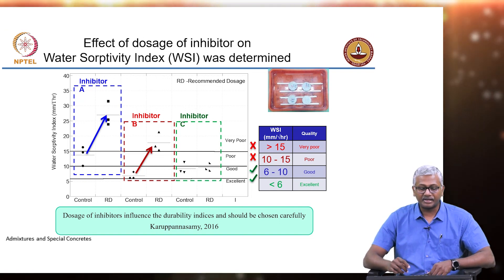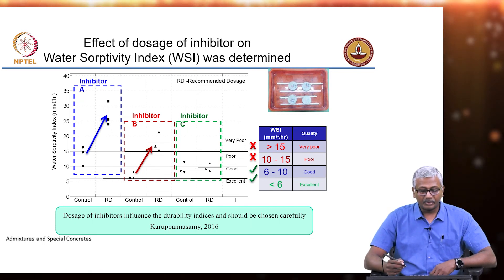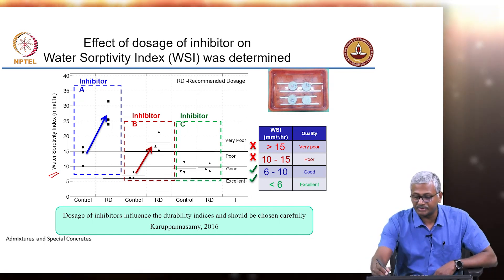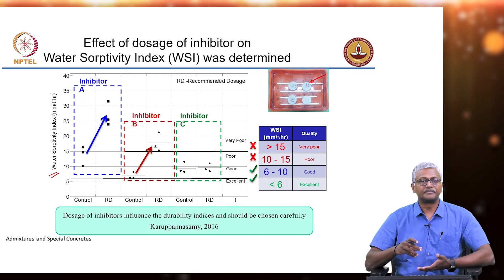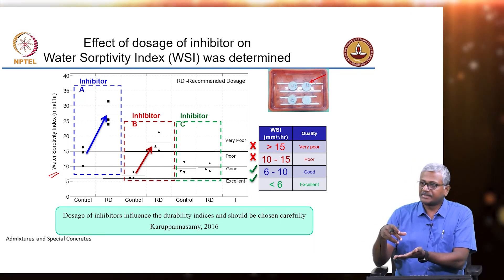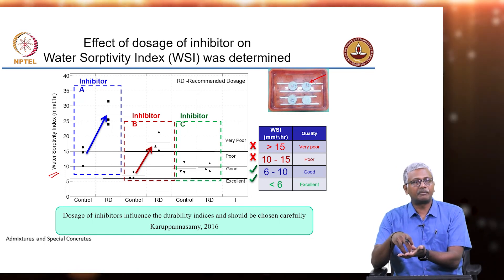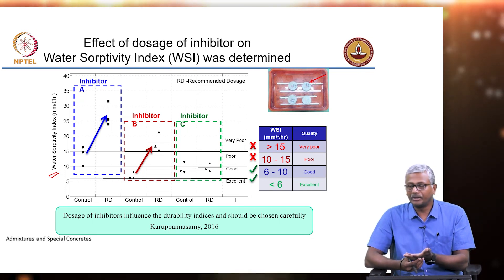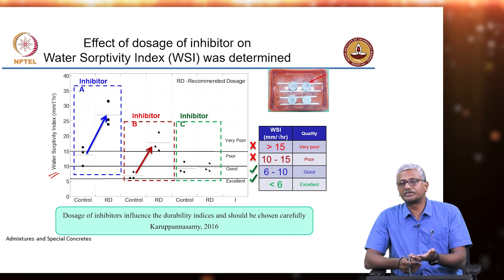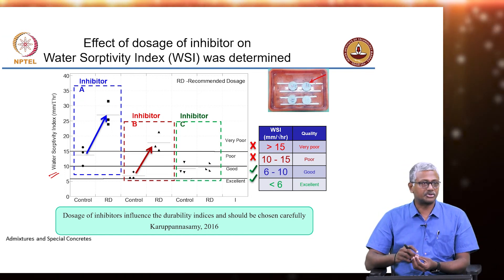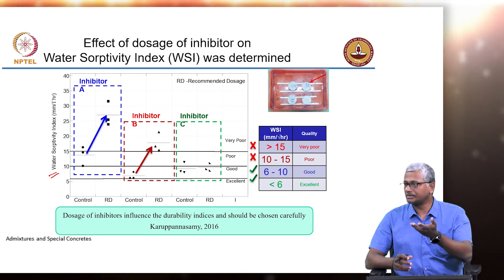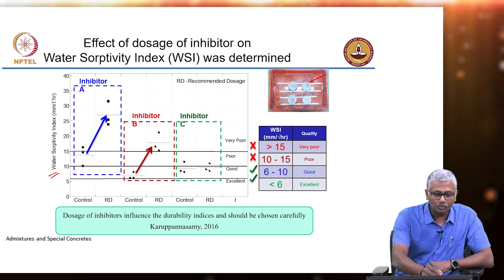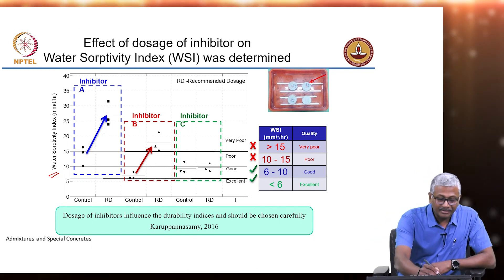Here there are three different types of inhibitors that have been looked at. You can clearly see that compared to the control values of water sorptivity — water sorptivity is a test where you take slices of concrete, expose the area, dry the slices so that they will be able to take in water by capillary absorption, then put them on a water tray. That water is basically imbibed by capillary absorption. So the more permeable or porous the material is, the faster it will imbibe moisture. And if the pores are connected, the capillary absorption will be significantly high. That is what is seen here — when you go from a control to an inhibitor system, you are increasing the water sorptivity index.